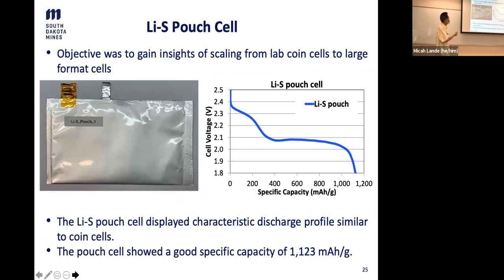We were curious that all the button cells or coin cells are small, laboratory scale, so they are not practical. So we did some preliminary work: what happens if we scale it up to a pouch cell, like this type of cell? When we discharge it, it again shows two characteristics, voltage profile plateaus, and in the end it delivers a good capacity, 1,100 milliamp-hours per gram. It's not as good as the coin cell, but it's a good number for the first initial try.